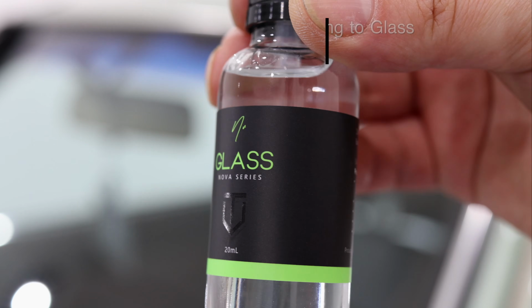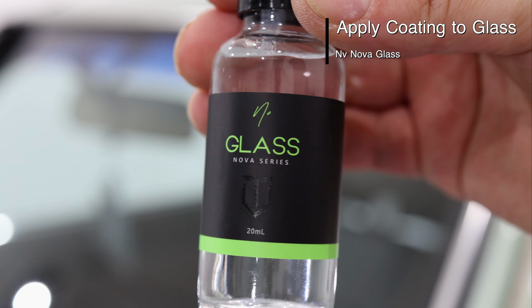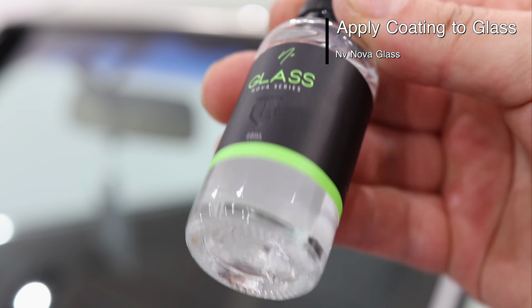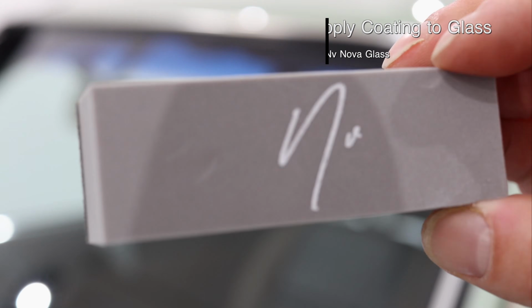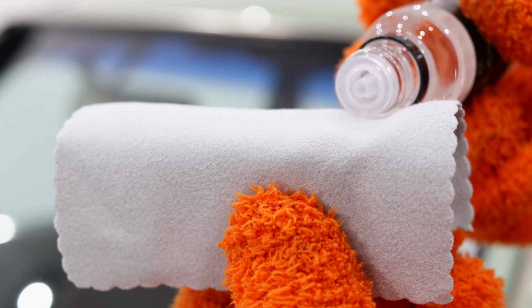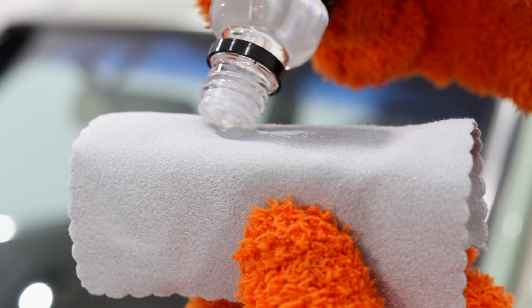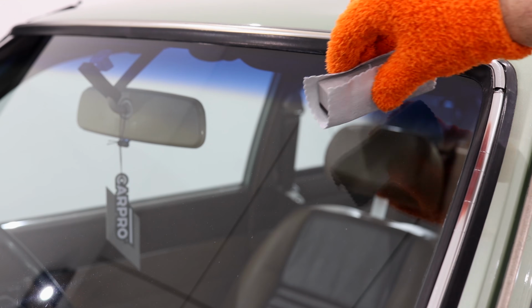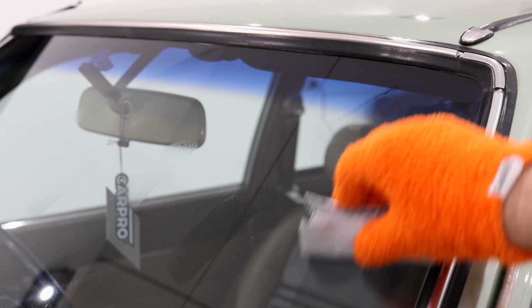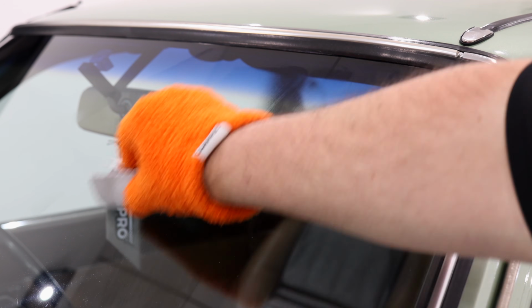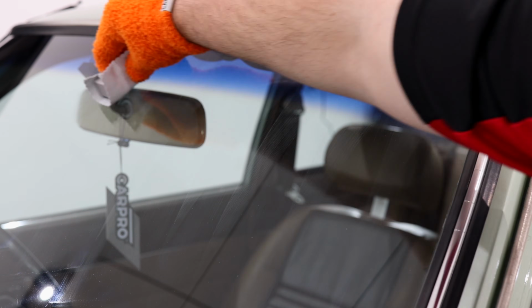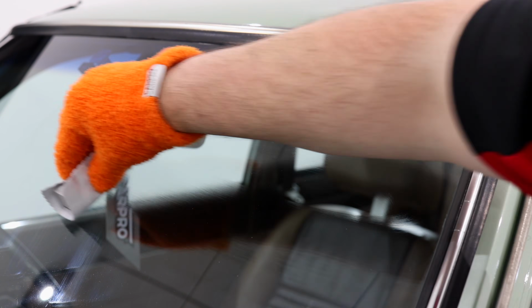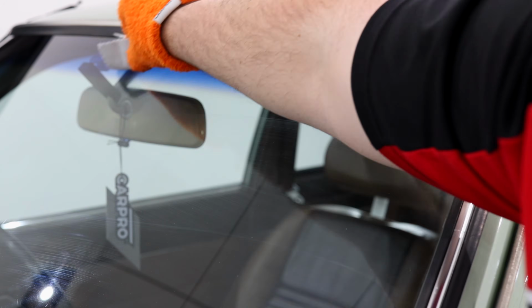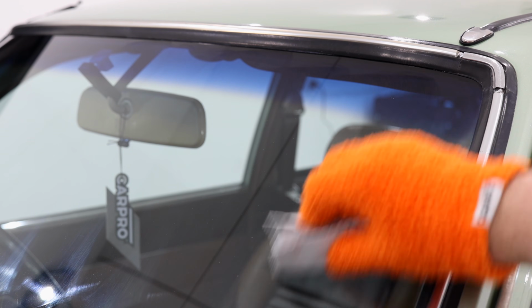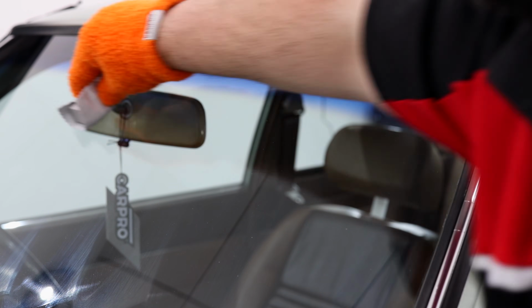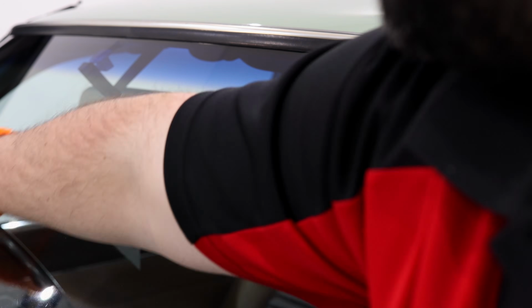Now, you should always follow the manufacturer's directions when applying a specific glass coating, but this general method and technique should work quite well for a variety of true ceramic glass coatings. Divide the windscreen into quarters and start by applying a bead of product on your applicator. Dab it into your section and then, moving a little quicker than you would with a paint ceramic coating, do 3 to 4 horizontal and vertical overlapping lines in your first quarter of the windscreen.